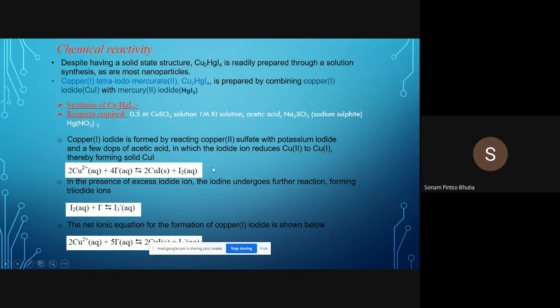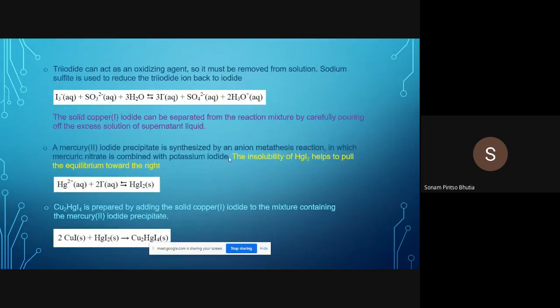The acetic acid dissociates the CuSO4 and potassium iodide into their constituent ions Cu2+, SO4 2-, K+, and I-, which further react to form the copper iodide in the solution. In the solution, there is an excess of iodide ions, so the iodide ions can further react with the formed iodine to give triiodide ions. These triiodide ions can act as an oxidizing agent, which can oxidize the formed product. So we add sodium sulfite to reduce the triiodide back to the iodide form. Now we cool the reaction mixture and separate the copper iodide by simply pouring out the excess solution of the supernatant liquid. The next part, we prepare the mercuric iodide.